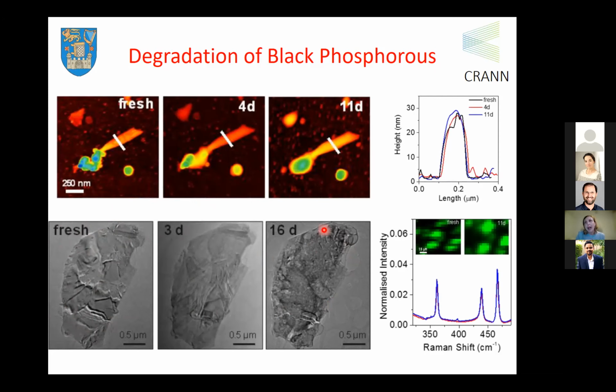You can see appreciable degradation after 16 days, but up to 3 days and a week, actually, we couldn't see any sort of degradation whatsoever. So we extended the shelf life of a material that would otherwise oxidize within hours.